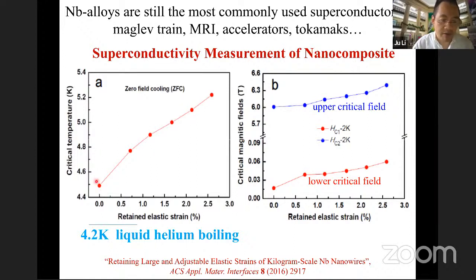Okay, so this is the experiment. The superconducting temperature shifted from about 4.5 Kelvin to about 5.2 Kelvin, by about 0.7 Kelvin. It doesn't sound like a lot, but remember that you're going to use liquid helium cooling. And so you actually increase the engineering margin for cooling these devices. And the other point is that the upper critical magnetic field and the lower critical magnetic field also improve quite a bit with the retained elastic strain.